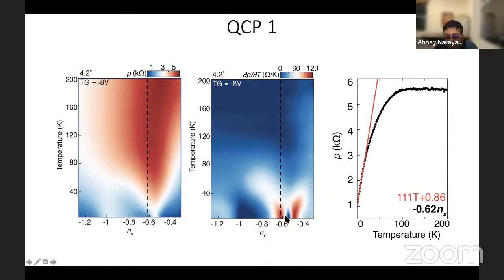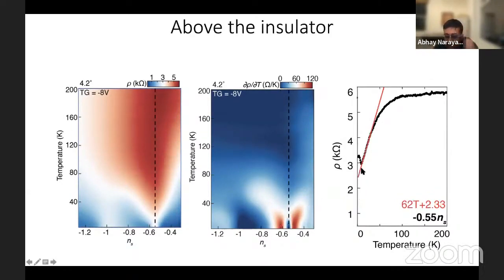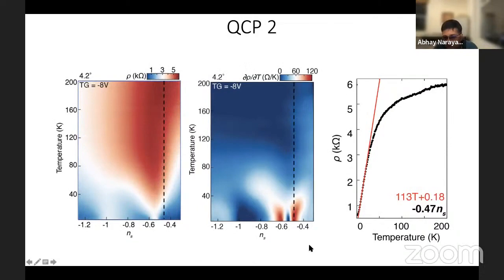So let me keep going along this direction. And here now I'm going to the insulating phase. And if you look at the actual insulator itself, then at low temperature, the resistance starts to go up, but just above the metal to insulator transition, once again, there's a little region of T-linear behavior after which the resistance rolls off. If I go over to the other quantum critical point,